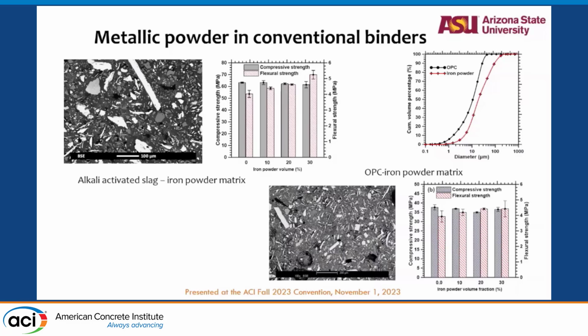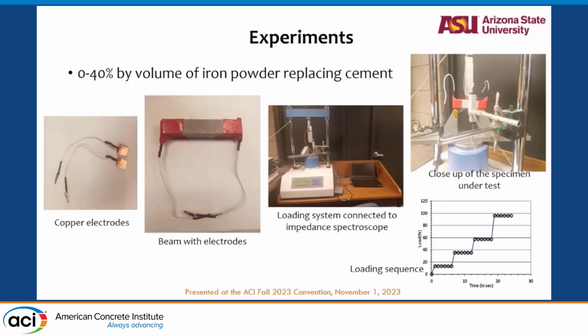So at least the incorporation of these powders into the mix is not showing any negative effect on the mechanical properties. Based on this, we moved forward with the mix from 0 to 40%. I'll mostly show what we got based on 40%. This 40% volume of iron powder was mixed into the concrete, and small beam specimens were prepared, where we attach electrodes onto both ends, insulate it with tape, and had a flexure test setup connected to the impedance spectroscope.